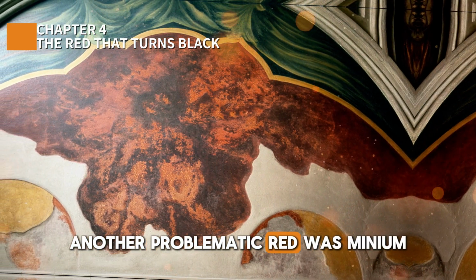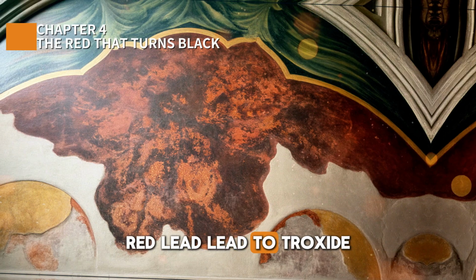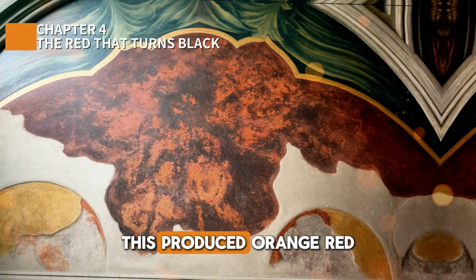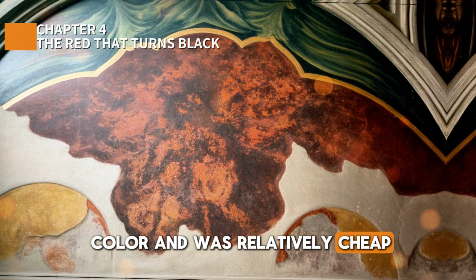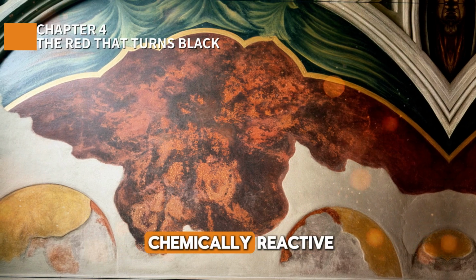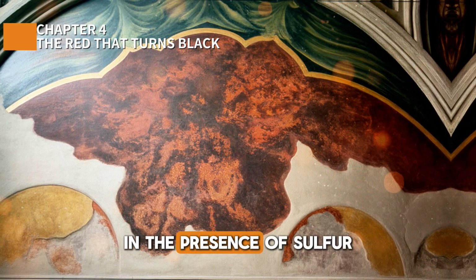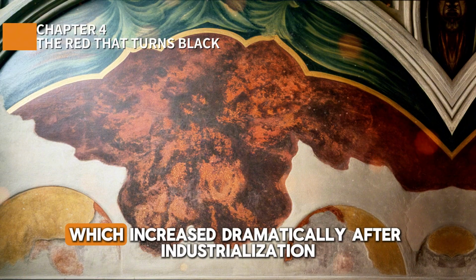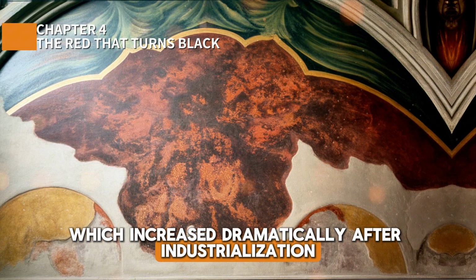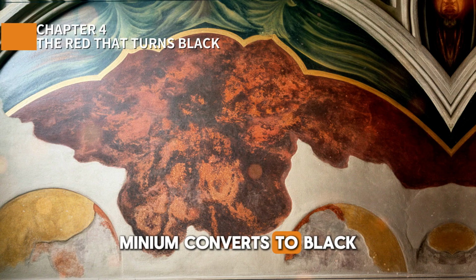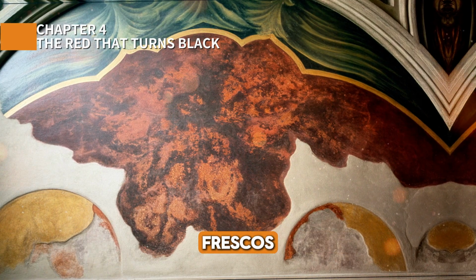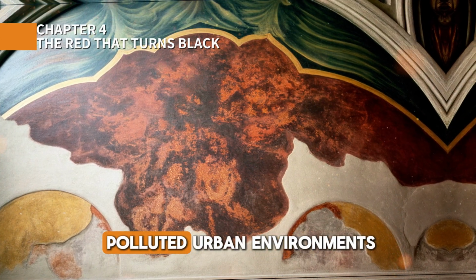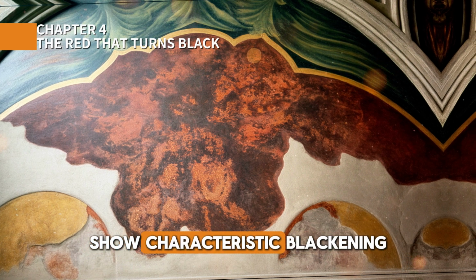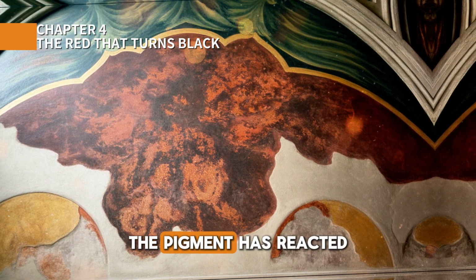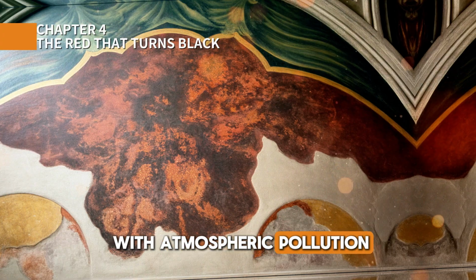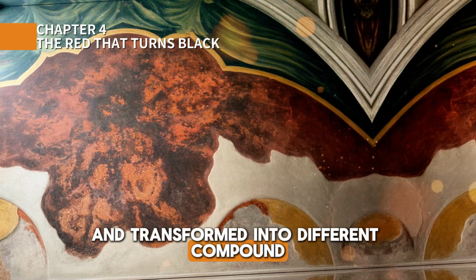Another problematic red was minium, red lead tetroxide. This produced an orange-red color and was relatively cheap. But lead compounds are chemically reactive. In the presence of sulfur-containing pollutants, which increased dramatically after industrialization, minium converts to black lead sulfide. Frescoes painted with minium in polluted urban environments show characteristic blackening. The pigment has reacted with atmospheric pollution and transformed into a different compound.